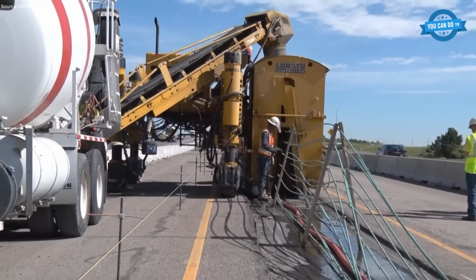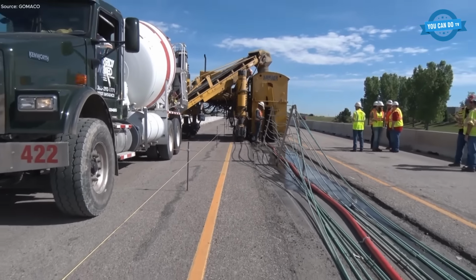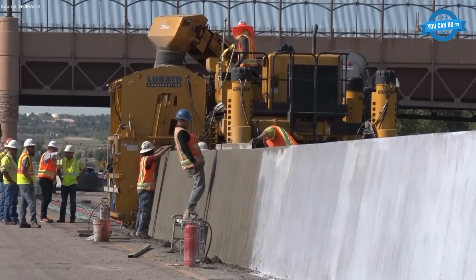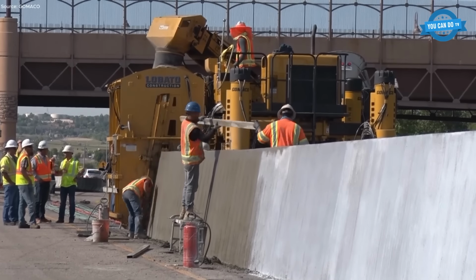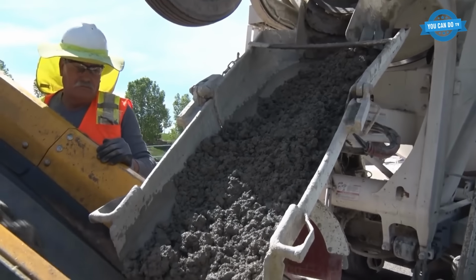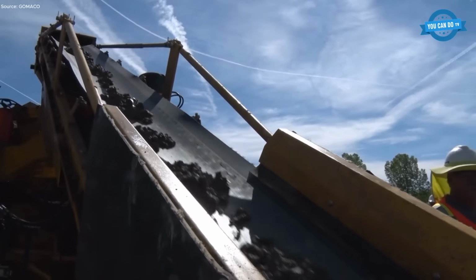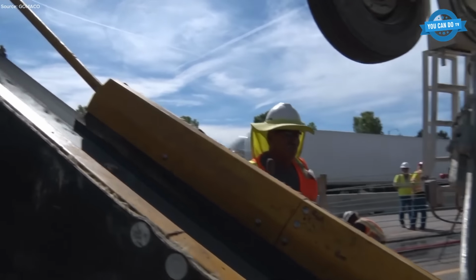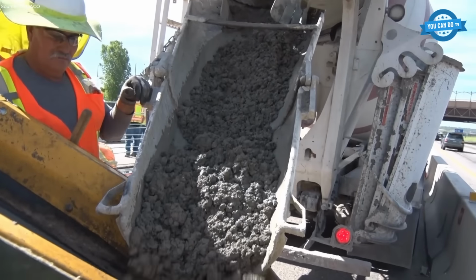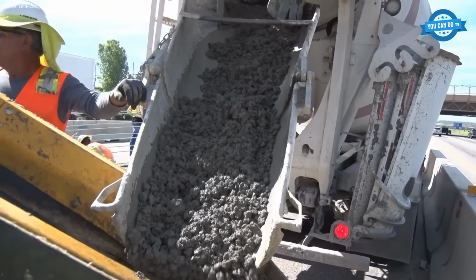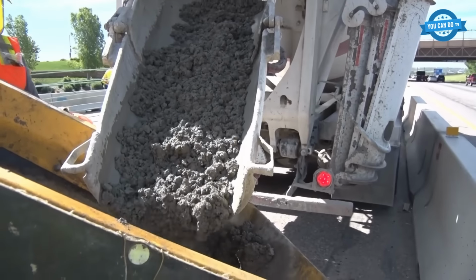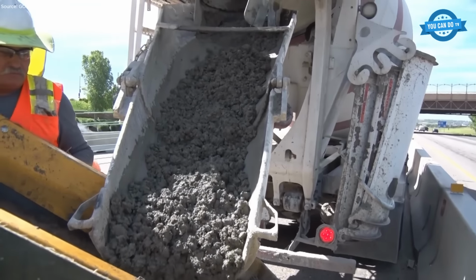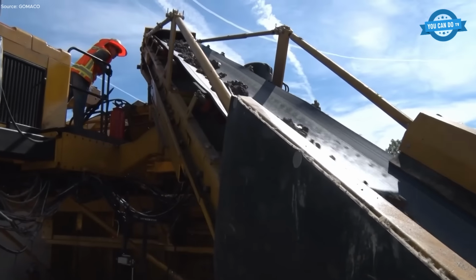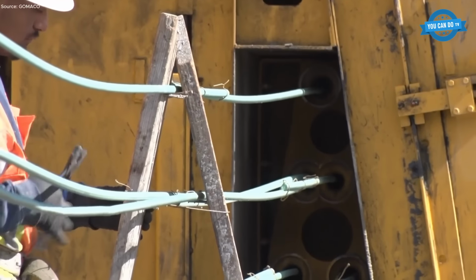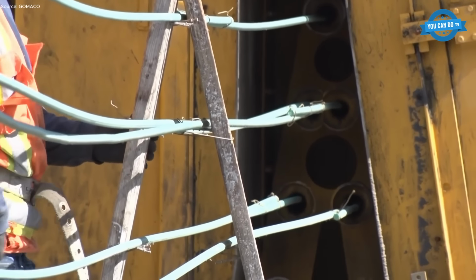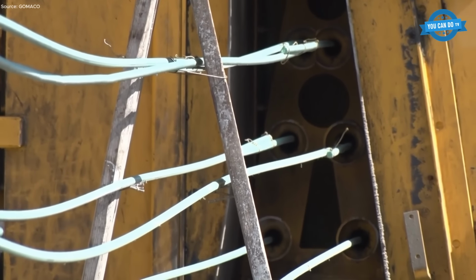Production spans nearly 15,000 linear feet, with daily output approaching 400 feet. Concrete control is critical. A low slump, half-inch wet batch mix ensures the barrier holds its shape as the mold advances. The glare screen incorporates 11 horizontal reinforcing bars, requiring careful staging and continuous monitoring to prevent movement during placement. Minor mold refinements have improved efficiency, reducing cleanup time and maintaining consistent surface quality. Precision alignment and disciplined finishing ultimately define the performance of this modern highway barrier system.